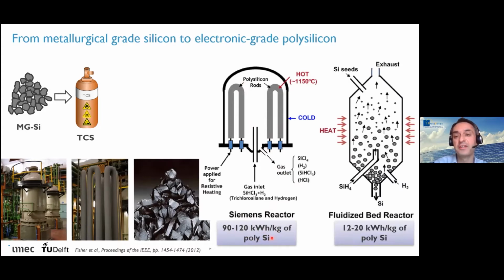So already for many years, people are investigating alternatives like the fluidized bed reactor, where you can reduce the amount of energy you need, because this is a really energy intensive and therefore expensive step. But whatever method you use, and the Siemens reactor is still the standard method, you end up with a polysilicon material, typically in the rod form here.